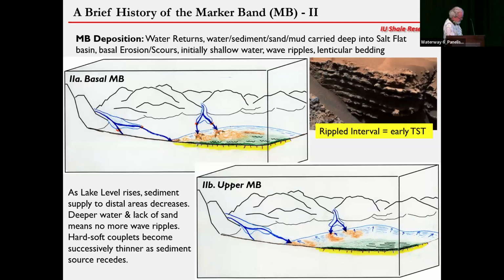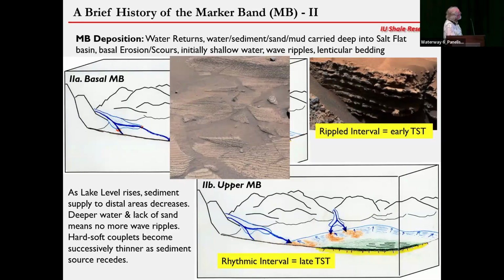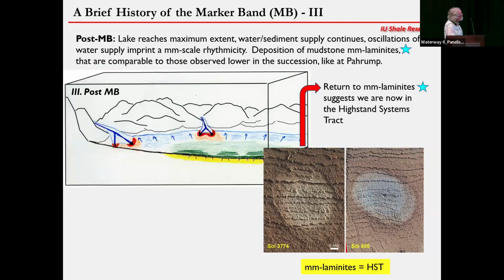And then the marker band deposition itself, we have basically the return of the water and sediment that gets carried deep into the salt flat initially. You get basal erosion that scours, shallow water, wave ripples forming, lenticular bedding, and all this kind of stuff. And then as lake level rises, sediment supply to the distal area decreases, deeper water, lack of sand means no more wave ripples, and then we go back to these hard to soft couplets that get successively thinner as we go up. Finally we end up in the last part, where these millimeter laminites look pretty much the same as you looked at before at the very base of the succession. Okay, so we go back into highstand laminites.